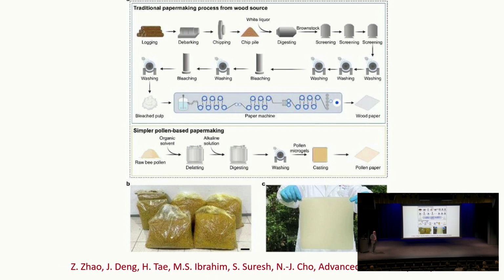If you compare the paper making process from wood versus paper making process with pollen, in the top, this is all the current steps that are used to make paper out of wood in industrial practice. Of course, the bottom process right now is only in the lab, done by students. It's not commercial scale. But the steps that are necessary, even at industrial scale-up, are relatively small. So it's much smaller. As a result of this, you have potentially substantially lower cost in doing this. So that's one advantage of doing this. We didn't intentionally make a cost estimate of this because you're comparing apples and oranges, a commercial scale versus a lab scale. But this is the step that's involved.